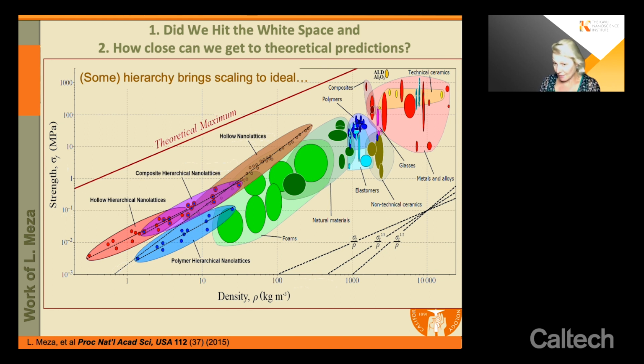Then the so-called bending dominated architectures allow you to be a little more efficient, in the sense that the power now is 1.5. So as you reduce your density by a factor of 2, your strength will be less affected. Now, the best type of architectures are the so-called stretching dominated solids. And here's this line. In fact, that is exactly what the theoretical maximum represents, this linear scaling. In the octet architecture, which is what I showed, when you reduce the density by a factor of 2, your strength will fall off by a factor of 2. So the question was about fatigue. These are our earlier points, and if you can follow this dashed line, you can very clearly see that it's much worse than the theoretical maximum. It certainly is not linear.